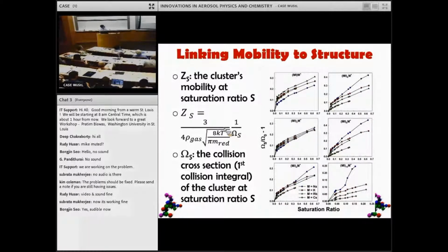And we can see very different behavior for different materials. For example, in this particular case, sodium iodide appears to not uptake a lot of water at small cluster sizes, but uptakes more than anything else at large cluster sizes. Conversely, cesium shows very little uptake overall, but actually even decreasing uptake as size increases. There also appear to be some clusters, the N equals 9 clusters, that uptake more water, and it's unanticipated, but we see very chemistry-specific, structure-specific, and size-specific behavior down at this scale.